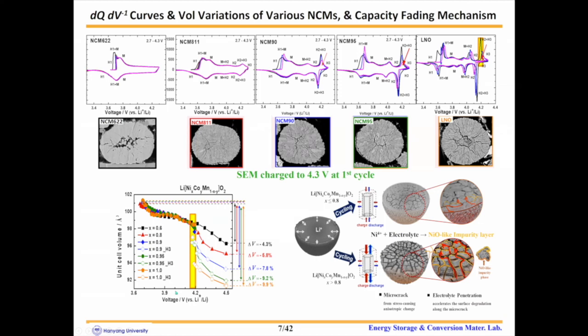This is the unit cell volume variation versus the charging voltage. The unit cell volume decreases monotonously up to 4.1 volt and then decreases rapidly above 4.2 volt, corresponding to the apex of the H2, H3 phase transitions. The unit cell volume variation increased with increasing nickel content. For example, this value is 4.3% for 622 and almost 10% for the pure LNO particles.